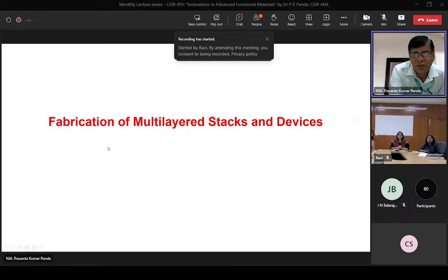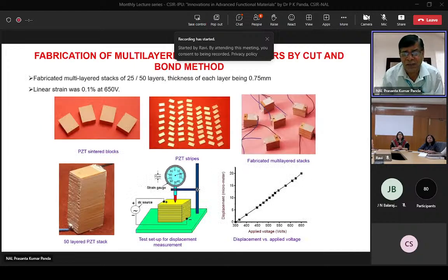Then coming to fabrication of multilayer stacks. What I have explained so far is the development of basic powders, PZT and PMN. But then we have to make them into devices in the form of multilayer stacks. In the initial years these were prepared by the cut and bond method, in a crude way. As you can see, we have done multilayered stacks here. Multilayering is mainly required to reduce the voltage requirement. So driving voltage can be reduced to less than 150 or 200 volts, so that they can be put in an aircraft with the available voltage. Otherwise, they require transformers, which is additional weight that cannot be entertained in an aircraft, because weight reduction is always a primary requirement.